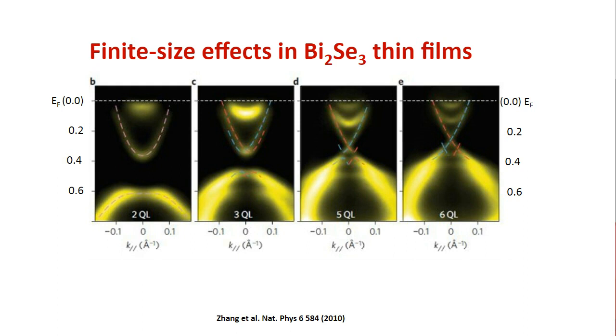You can see the 6 quintuple layer bismuth selenide clearly shows the surface states, and the surface states are touching each other. You can see those 2 straight lines crossing each other. As you go below 5, when you go to 3, you can see those surface states are no longer touching each other. There is a gap in the surface states. When you go to 2, this gap is even stronger, right? So 6 quintuple layer bismuth selenide is showing basically the bulk electronic structure. When you go to 3 and 2, the surface states also develop a gap.